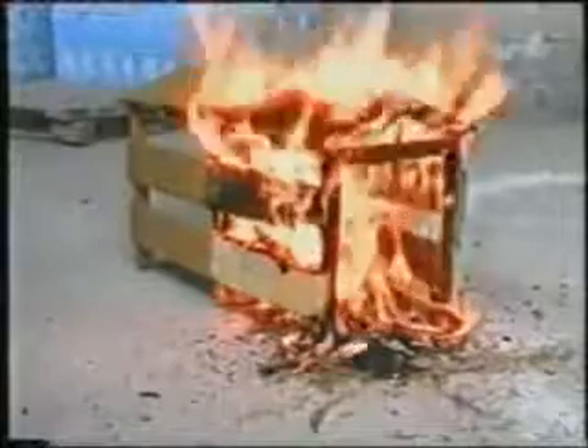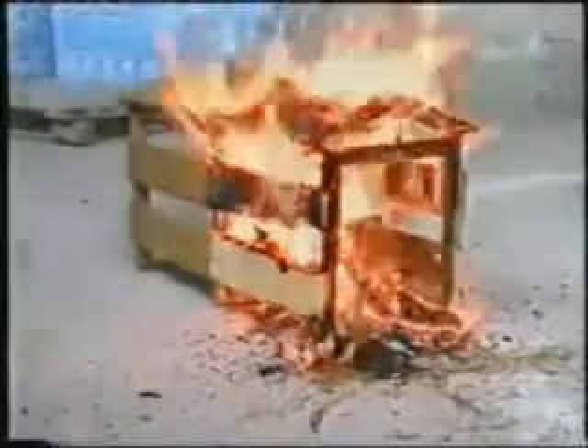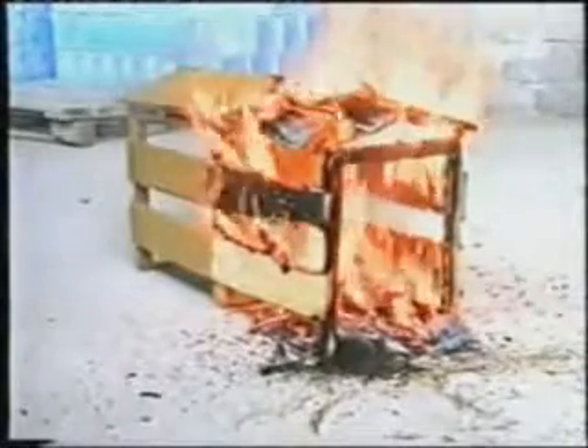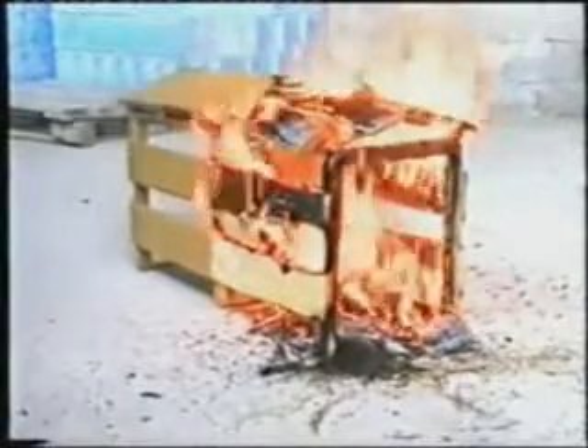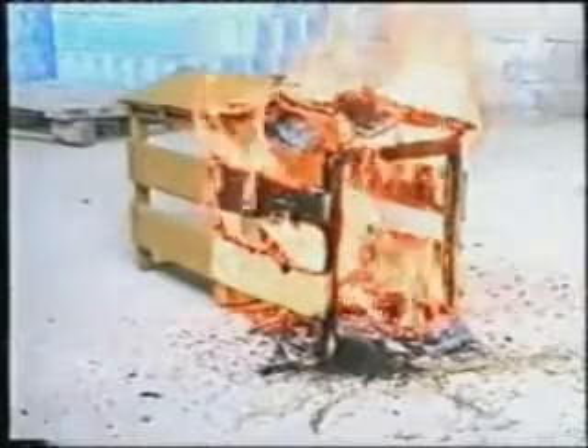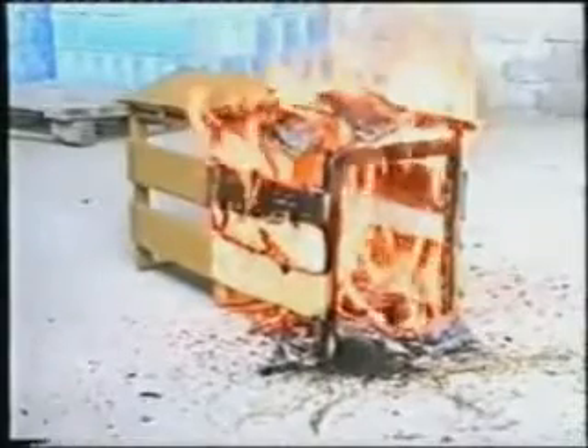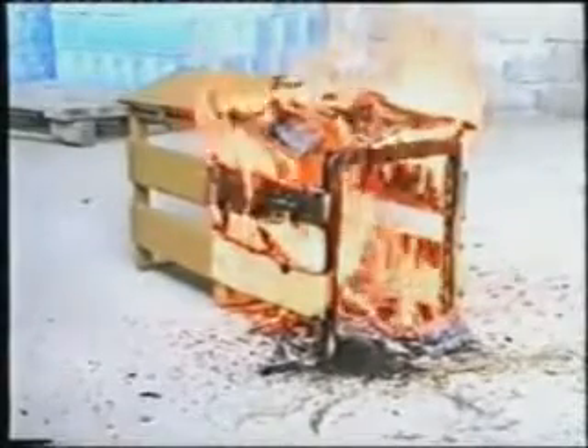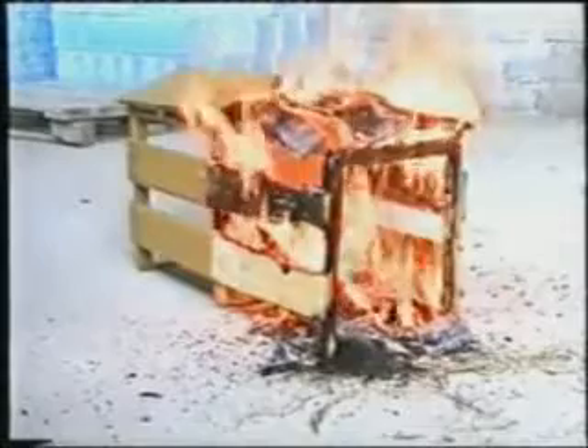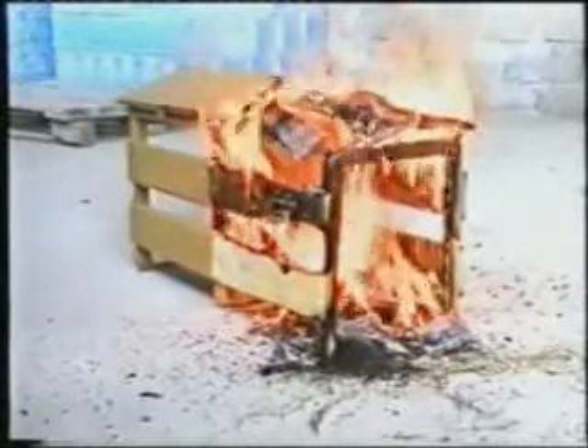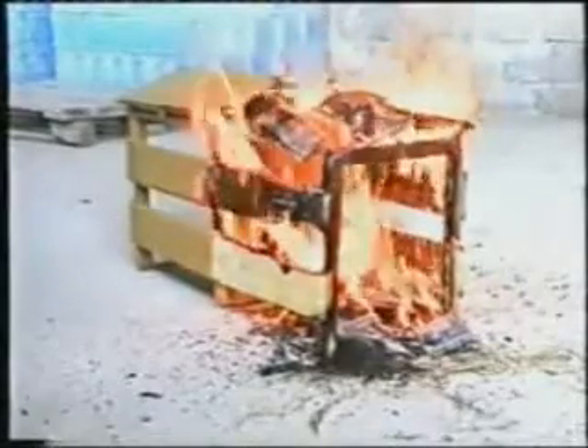When exposed to flame, the wood which is coated with this coating emits carbon dioxide and the water contained inside, but the coating has elastic attributes, so those gases are localized in it, making gas swellings similar to blisters on the skin, which can be of different size depending on the material which is coated, and they do not crack open and neither separate from the coated material.